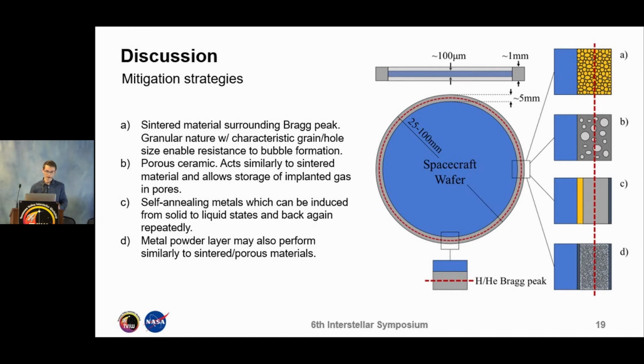So you can resist bubble formation that way. A similar method is to use a porous ceramic, which allows the storage of implanted gas atoms in its pores. This is shown in B. In C, we show a self-annealing metal, which can be induced from solid into liquid and back again. This enables trapped gas to not aggregate and form bubbles, and you can let it diffuse out. And then a similar scheme is a metal powder, which will act similarly to a sintered material with its grain and hole size, making it resistant to bubble formation.